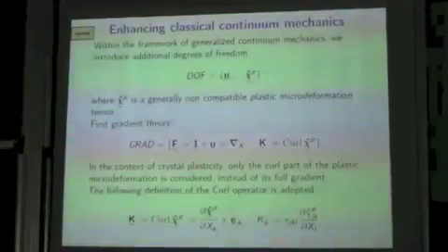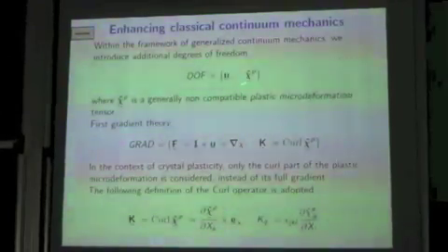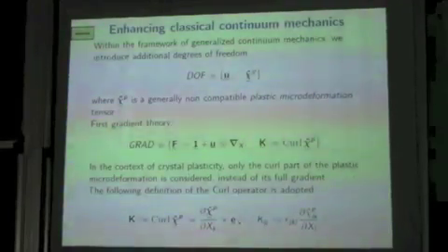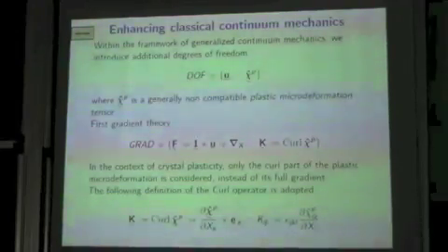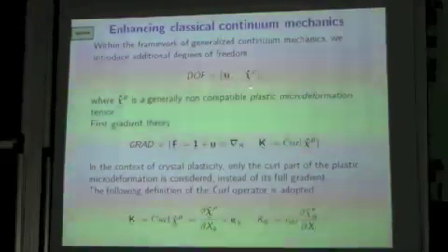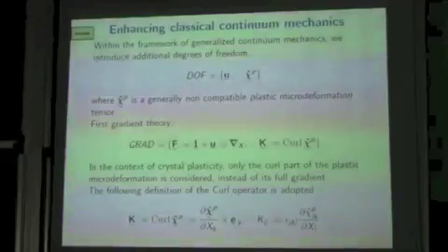Okay, so the microcurl model is based on Eringen and Mindlin's micromorphic theory, in which you have not only the possibility of translation for the material point, but also the possibility of an affine transformation of three directors that can rotate and that can also distort, in fact. And so this affine transformation is represented by a second order tensor. That's why you have a tilde like this here. It's non-symmetric, because you have rotations and you have stretch.